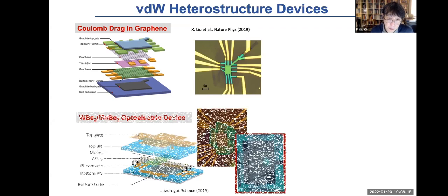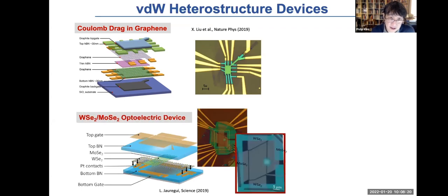For example, you can also replace the graphene with, say, a semiconductor. In this particular case, we have P-type and N-type transition metal dichalcogenide semiconductors, such as molybdenum and tungsten diselenide, making a PN junction, an atomically thin PN junction. You can think of this as an atomically thin PN diode, which again can be controlled by the top and bottom gates to tune the chemical doping, the carrier doping levels, continuously by just using the gate voltages.